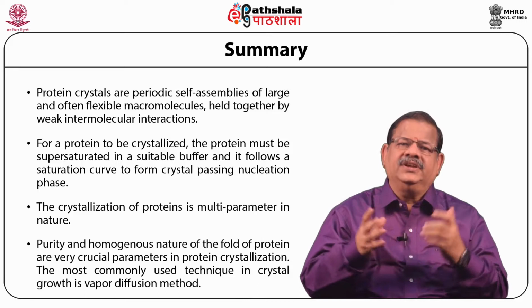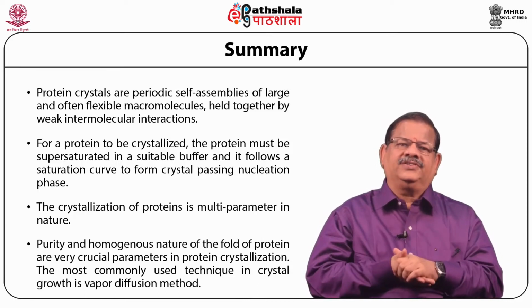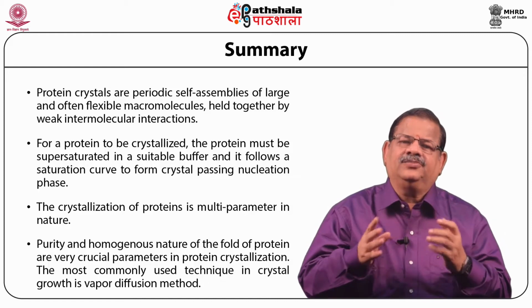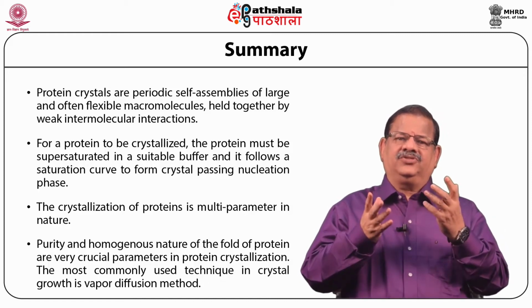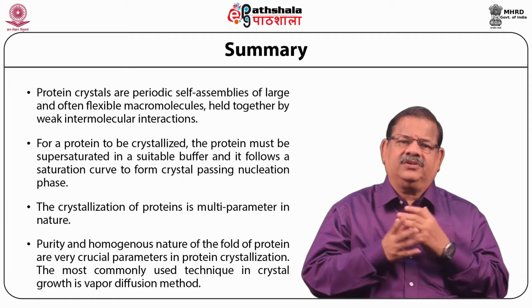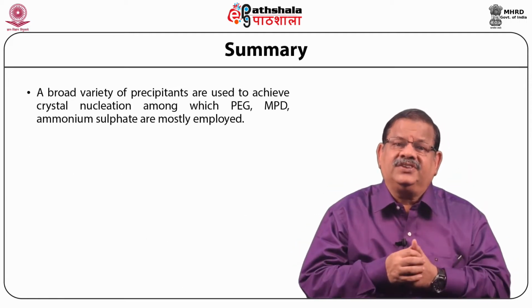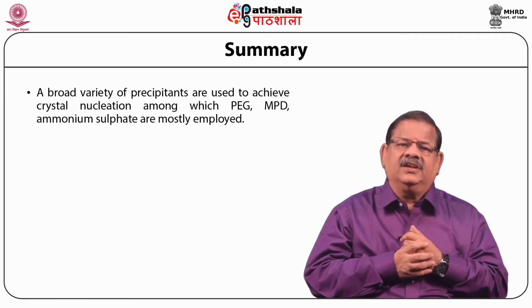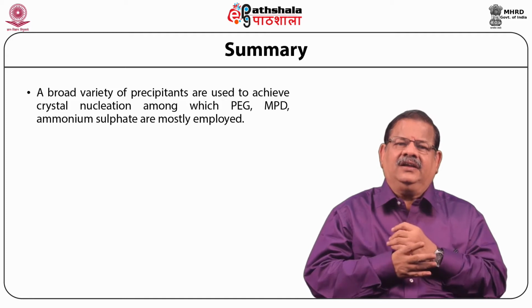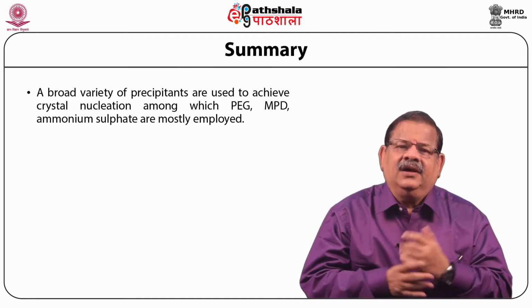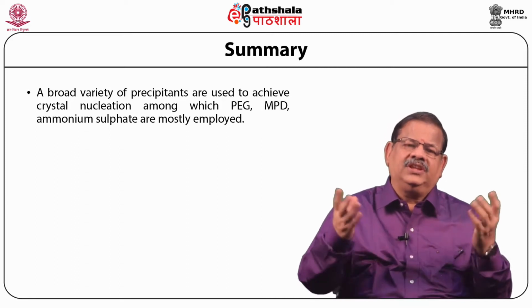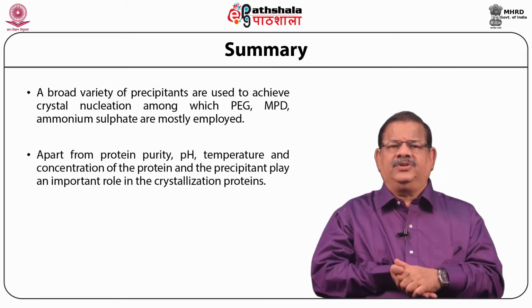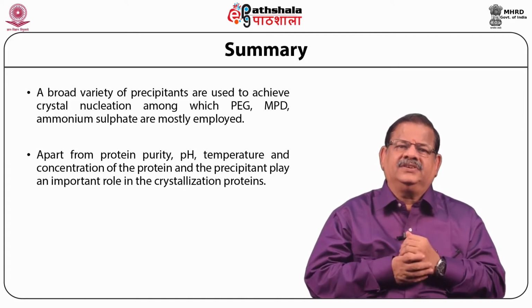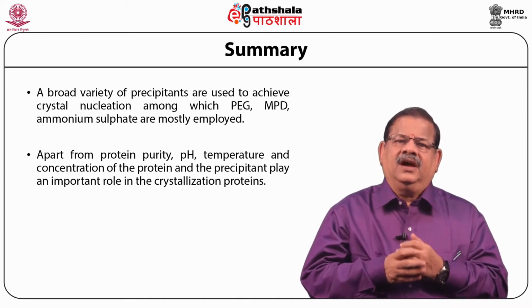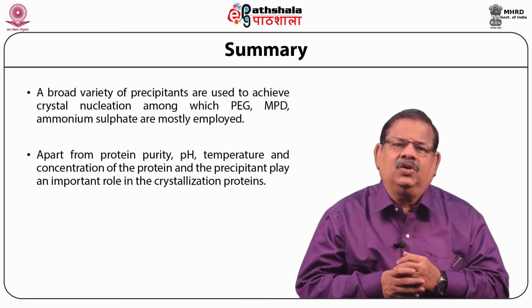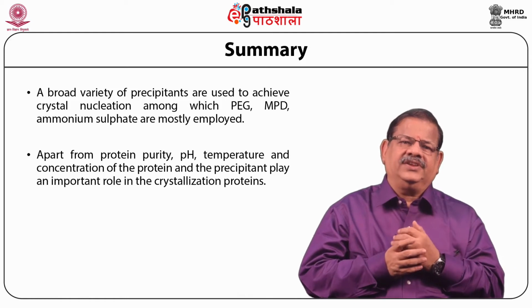Purity and homogeneous nature of the fold of proteins are very crucial parameters in protein crystallization. The most commonly used technique in crystal growth is the vapor diffusion method. A broad variety of precipitants are used to achieve crystal nucleation, among which polyethylene glycol, PEG, MPD, and ammonium sulfate are mostly employed. Apart from protein purity, pH, temperature, and concentration of the protein and the precipitant play an important role in the crystallization of proteins.